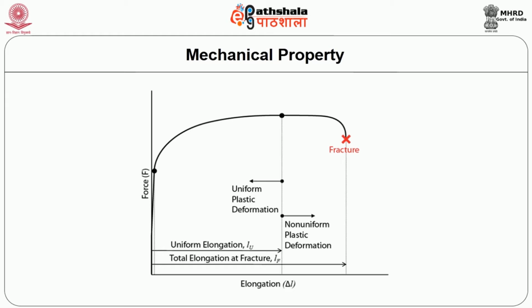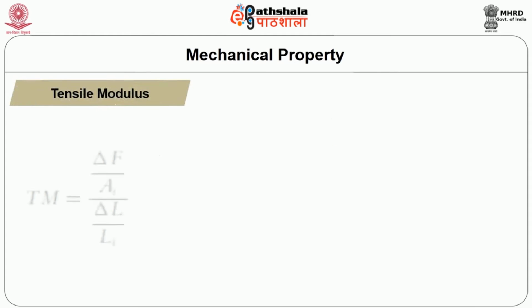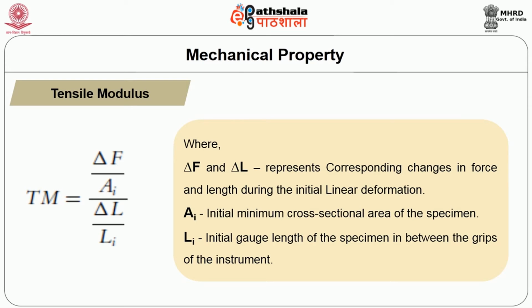So if you look at the details in figure 1, basically figure 1 is obtained by plotting the resulting elongation of the packaging material on the x-axis and the applied load on the y-axis. The curve thus obtained is called the force elongation curve. The important mechanical properties include tensile modulus, tensile strength and percentage elongation. Tensile modulus is represented as Tm and is calculated using the following formula. Tm is equal to delta F divided by Ai, whole divided by delta L divided by Li, where delta F and delta L represent corresponding changes in force and length during the initial linear deformation, Ai is the initial minimum cross sectional area of the specimen, and Li is the initial gauge length of the specimen in between the grips of the instrument.